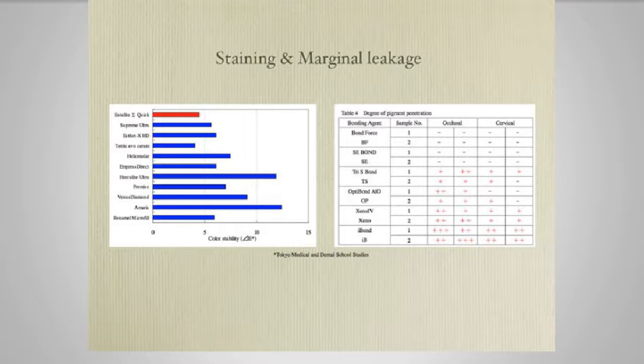degrees for 24 hours. And the table there shows what kind of pigment penetration happened with these different adhesives. So the two adhesives that did the best were bond force and SE bond, as the others all had some form of micro leakage.